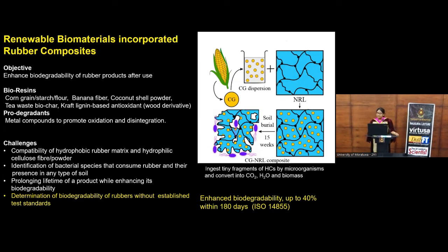Another successful research that is applicable for the rubber industry was incorporating biomaterials into rubber composites. Many biomaterials were incorporated into latex as well as dry rubber, because my research was broad and covered both the latex industry as well as the rubber industry. Corn derivatives, banana fiber, coconut shell powder, as well as tea waste biochar replacing carbon black were used, and wood derivatives were used as antioxidants in the solid tire industry.